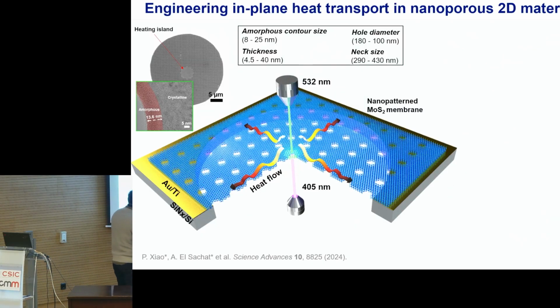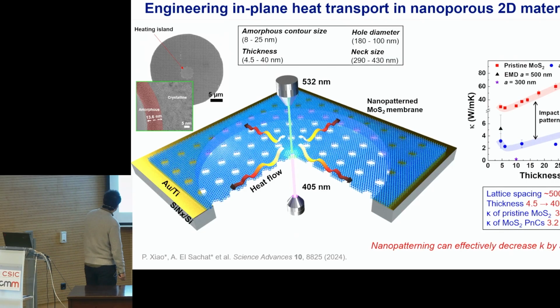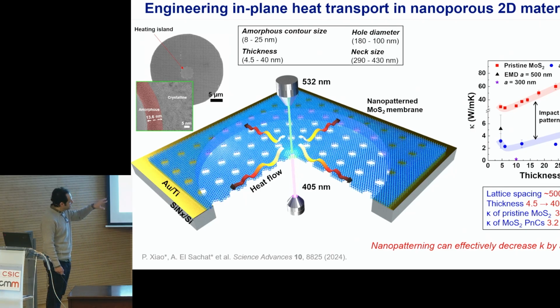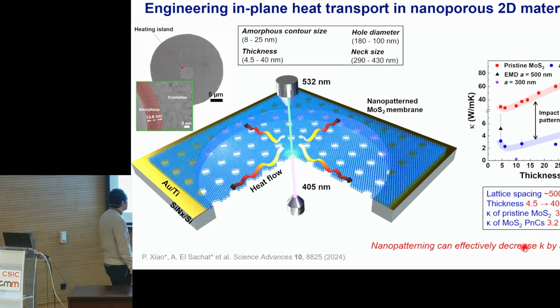Okay. The other interesting thing is that we did also this in 2D materials and it's working the same. And you see here how the nanopatterning on top of the molybdenum disulfide flakes decreases the in-plane thermal conductivity. The pristine MoS2 goes from 32 to 88 watt per meter Kelvin. But then, if we create some phononic crystals on the top, this thermal conductivity can be decreased by a factor of 10.